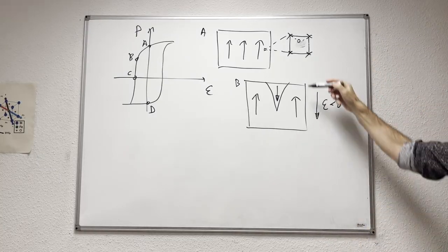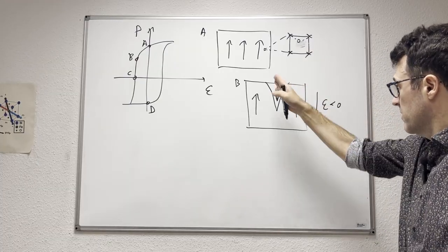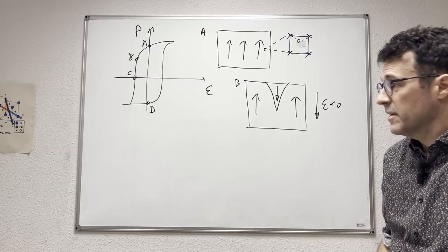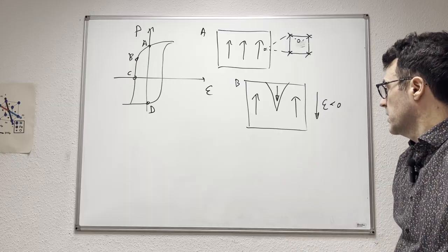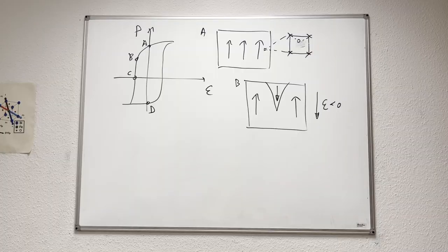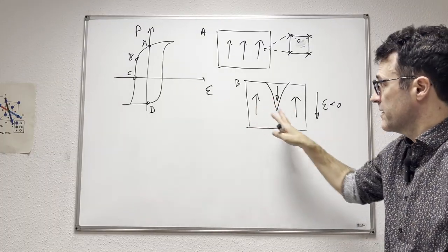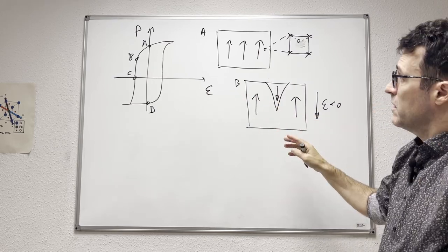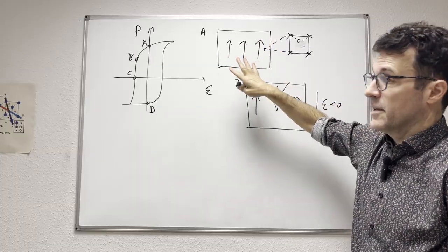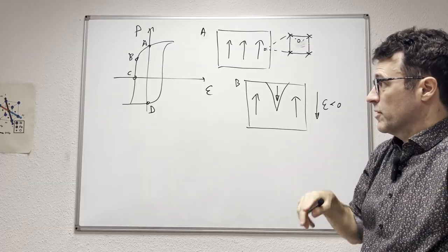Okay. So you nucleate this kind of transformed domains. They tend to have the shape that I have drawn there. That's not arbitrary. That's because as much as possible, the system typically avoids forming charged domain walls, but that's not very important here. It's only important to remember that you have intermediate states where the polarization is not homogeneous at all. Right? If you see this, you could imagine that maybe the polarization becomes smaller everywhere in the sample in a homogeneous manner, right? To go from A to B. But that's not what happens at all.